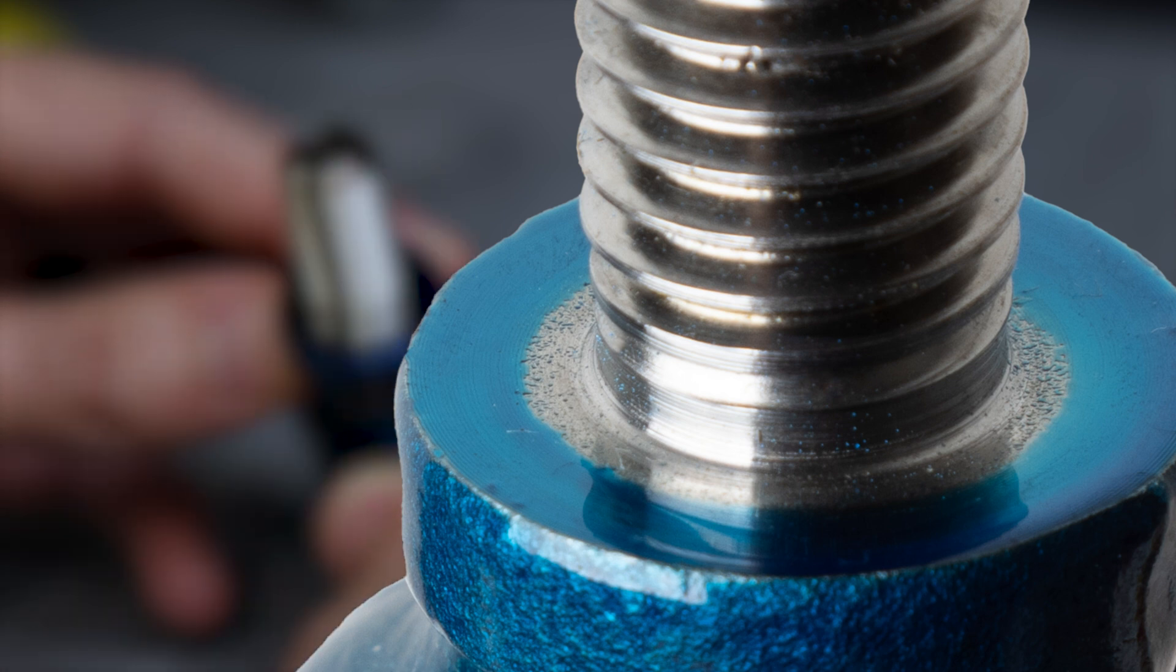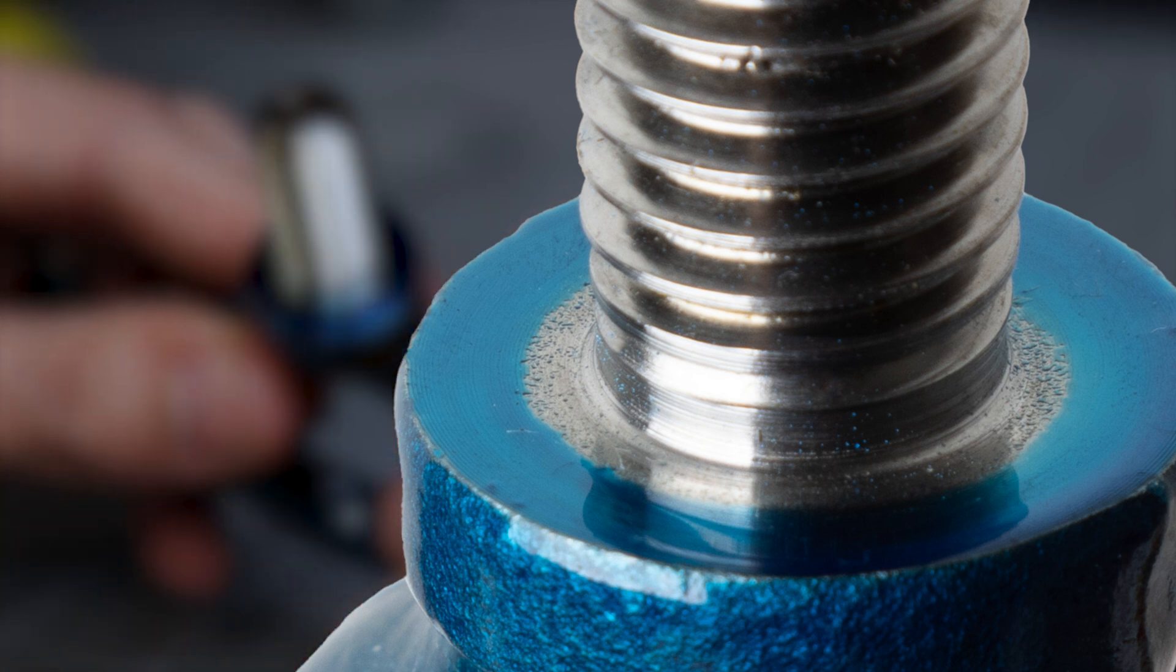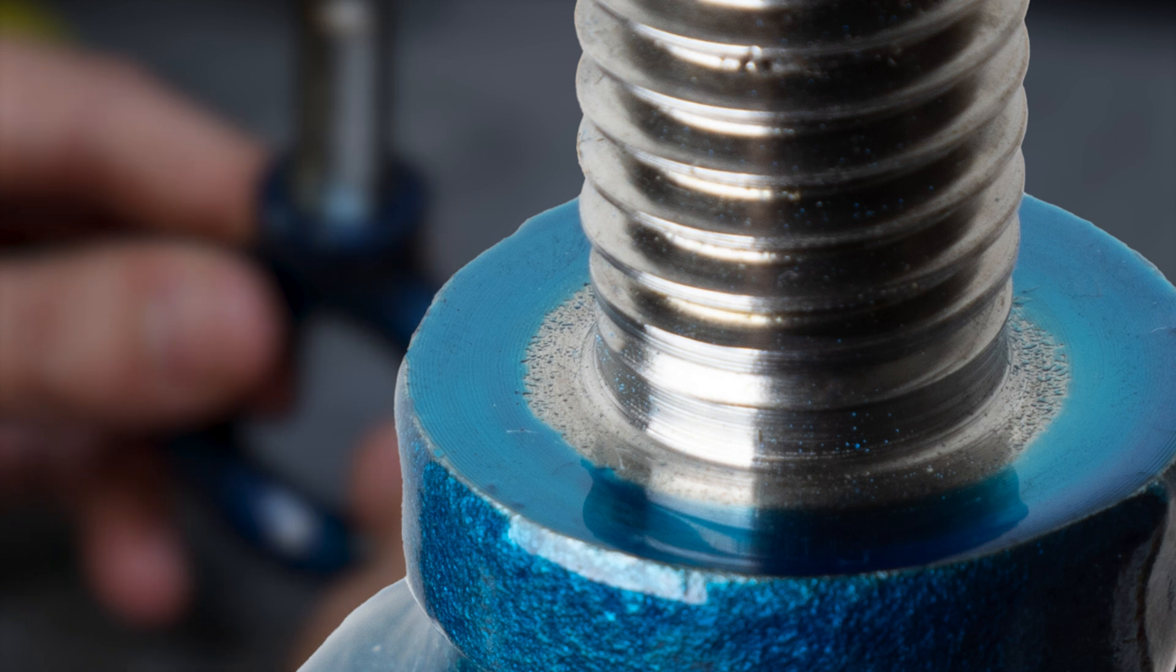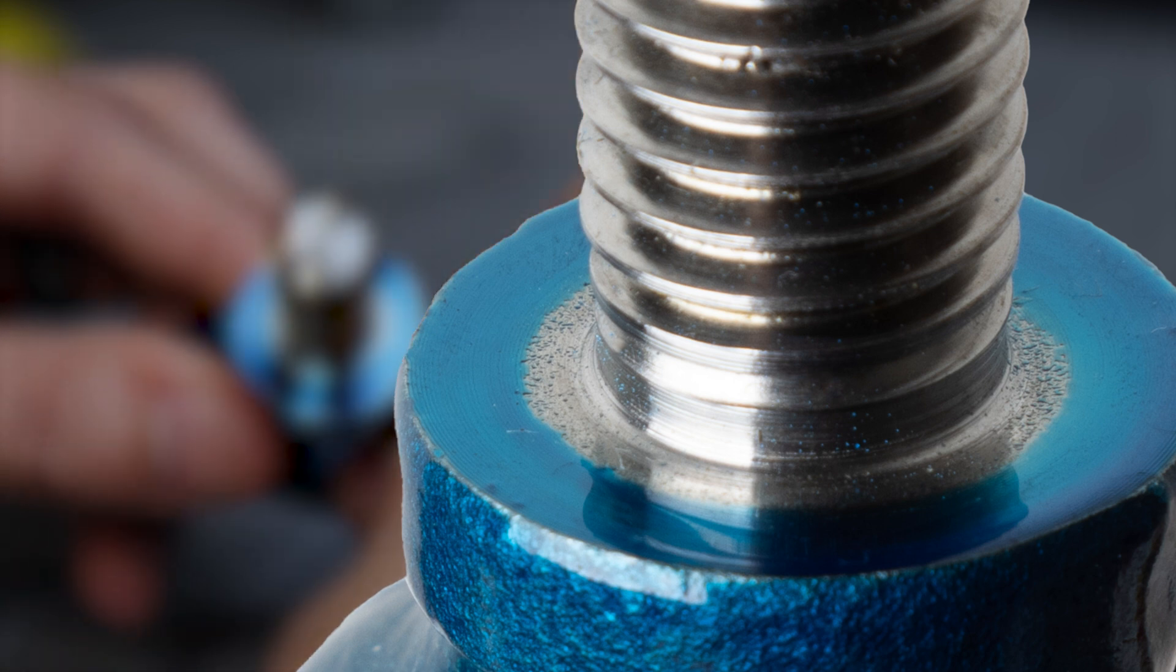So in the end this method actually can work to prevent powder buildup but it will likely result in inconsistent lines based on how the cap is installed and the pressure of which the powder is applied.